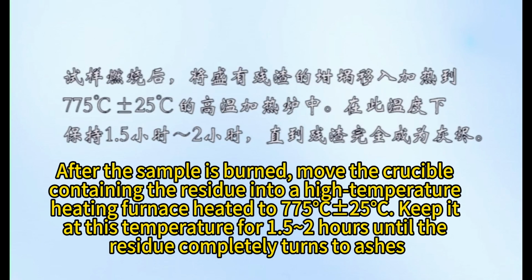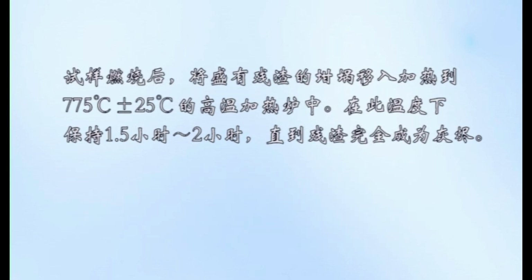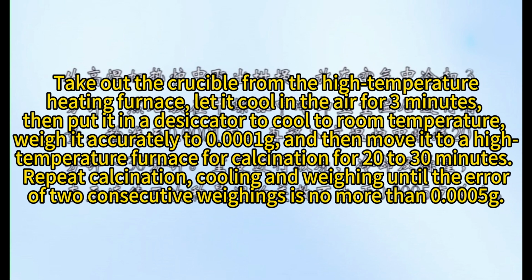After the sample is burned, move the crucible containing the residue into a high-temperature heating furnace heated to 750 to 800 degrees centigrade. Keep it at this temperature for 1.5 to 2 hours until the residue completely turns to ashes. Take out the crucible from the high-temperature heating furnace. Let it cool in the air for 3 minutes. Then put it in a desiccator to cool to room temperature.